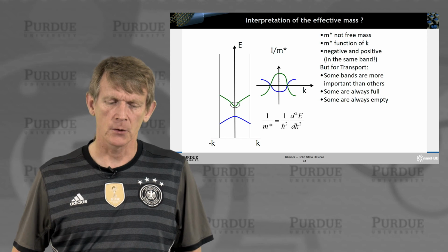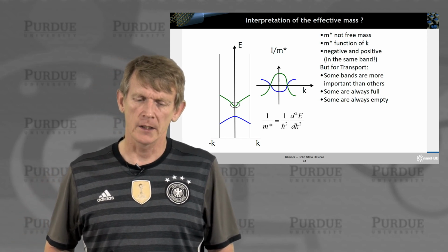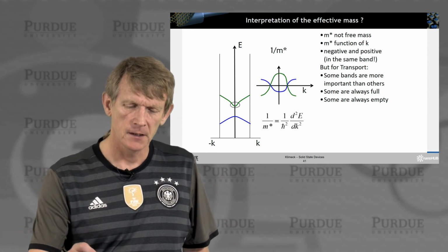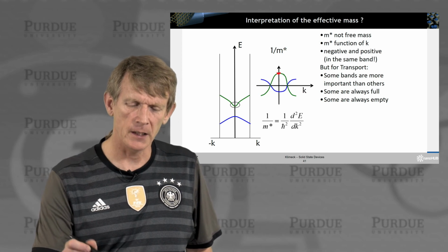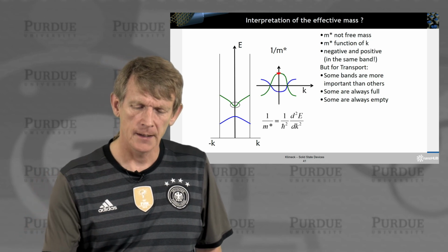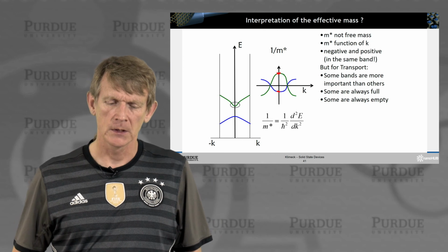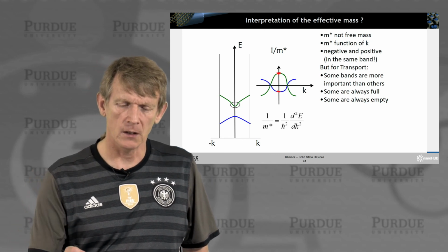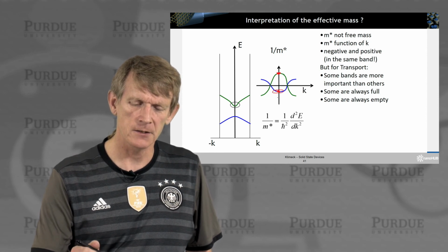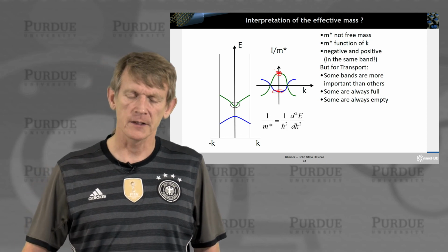All right. So in here, we can do a little bit more interpretation where the effective mass of the conduction band at close to k equals 0 is positive, and it has a certain value. And it is negative for the holes at k equals 0. And as I mentioned before, we often, for large structures, focus on a K range that is very small, where the effective mass is then roughly constant.